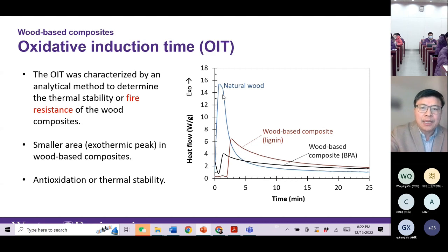Natural wood can be oxidized or ignited within 1 to 2 minutes. But with our wood-based composite with the lignin-based epoxy resin, we can extend that time to about 3 to 4 minutes. Also, the peak area shows how much heat is released, how much oxidation heat. This peak area is much smaller compared to natural wood, meaning the oxidation reaction is much suppressed by this wood-based composite material. That's another good property in terms of application, which means it has some fire resistant property.